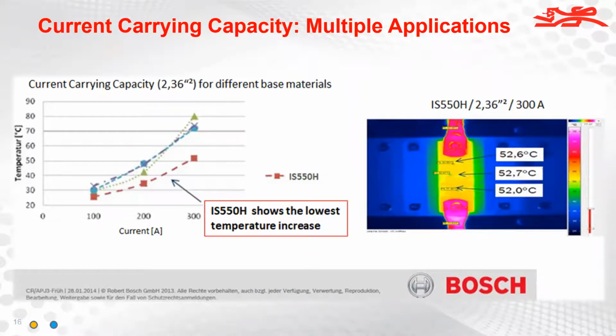Yeah, Chris, and this is a good example of how this material handles the heat in the current carrying capacity. Obviously, with fast charging systems, you're going to try to push as much current through your system as you can to be able to get that product to help charge your vehicle much more rapidly. This compares some typical FR4 materials to the IS550H, and this is really a result of the thermal conductivity of the material. Typical FR4s are about 0.35 watts per meter K, but when you look at this material, you're talking about a 0.7. So it's almost double the thermal conductivity, which allows this material to move heat away from the devices and reduce the amount of energy that remains near the components and allows you to get the heat out of that material more rapidly.